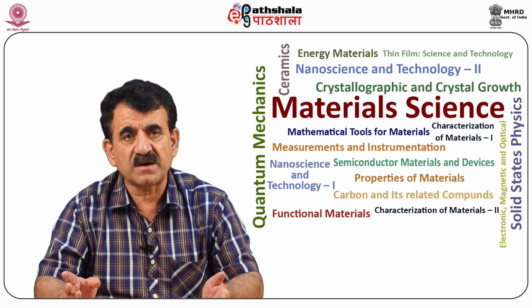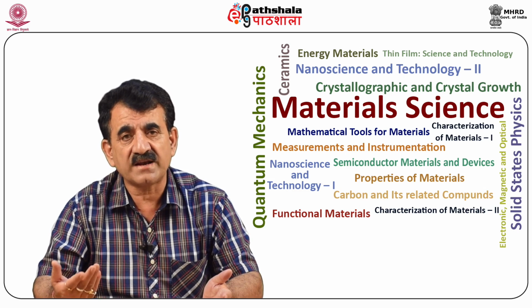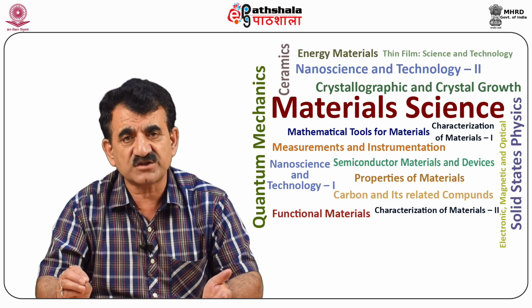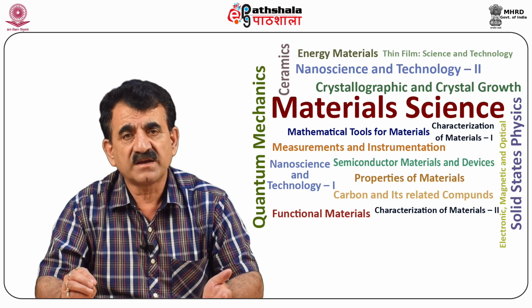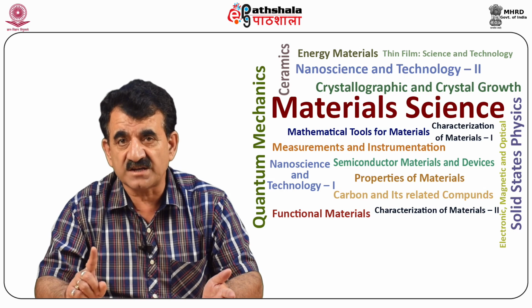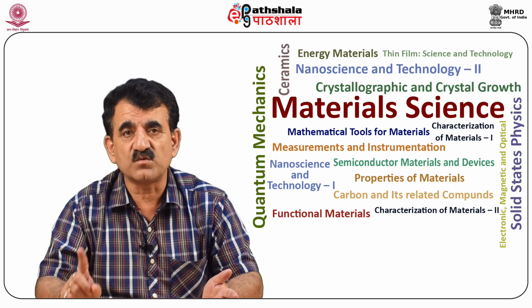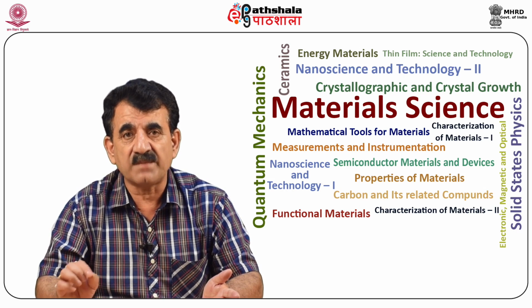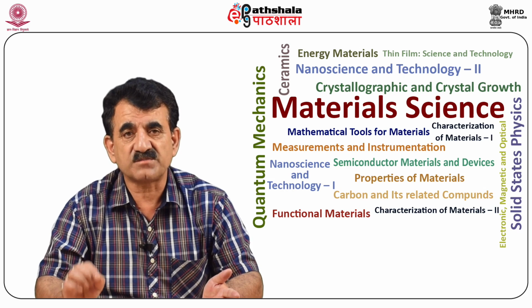So this is a comparison of properties of the most applied isotopes, as I mentioned, iron and iridium. This is the host, so iron host and iridium host, whose energy for iron, as I mentioned, 14.4 keV is the threshold which acts as a probe, and 129 keV for iridium. And as I mentioned, the recoil free factor is 0.91 and 0.06. So this is also very important. These two, energy and the recoil free factor, are two important parameters to authenticate this spectroscopy.